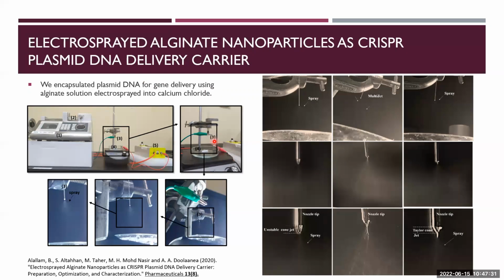Alginate has very large pores, and the material can easily escape out from the particle. So you will get low encapsulation efficiency. It took quite some time to find the suitable parameters that can get the plasmid DNA encapsulated inside the particles. And when we are talking about nanoparticles, the surface area is very large, so the material can escape very easily. But we encapsulate this plasmid DNA in quite high efficiency.